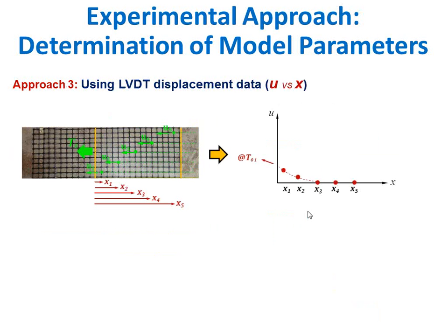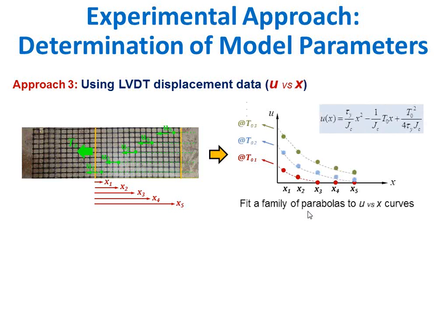So potentially we can fit a parabola to the displacement function, and instead of getting one property at each point, we need all the points, but we fit one parabola and we do get the parameter, the stiffness. We have tried all three, and they give very consistent results. It's the same data set. Currently, the one that we are proposing, because it's the simplest, is just to plot it and get the slope of a curve, and that's how we are getting it.